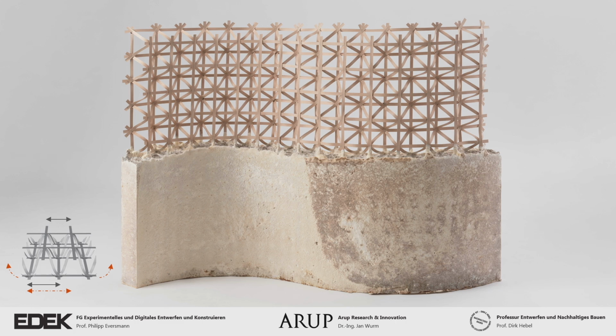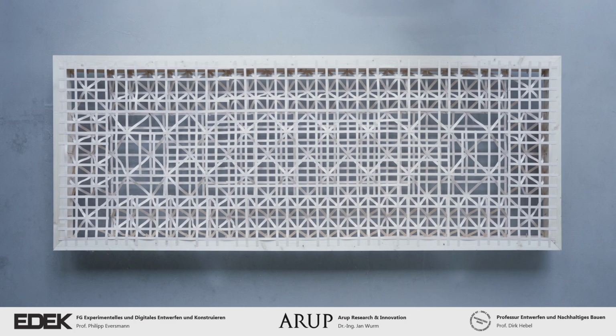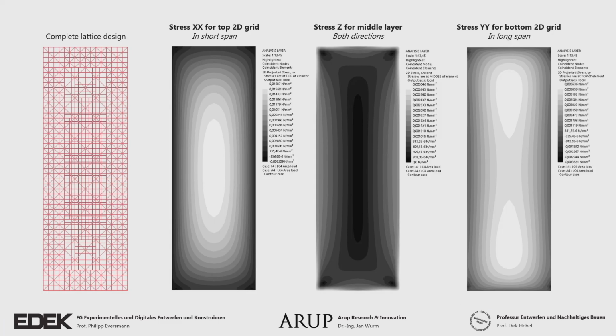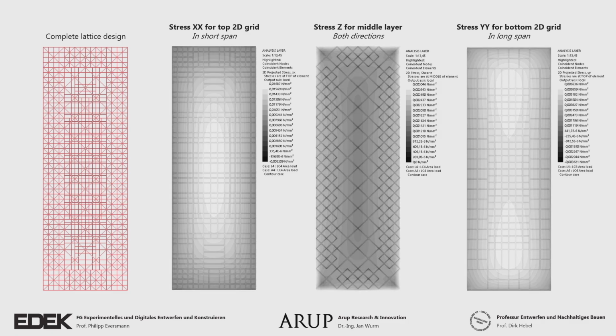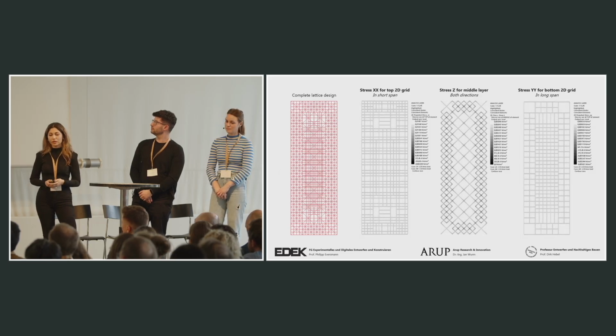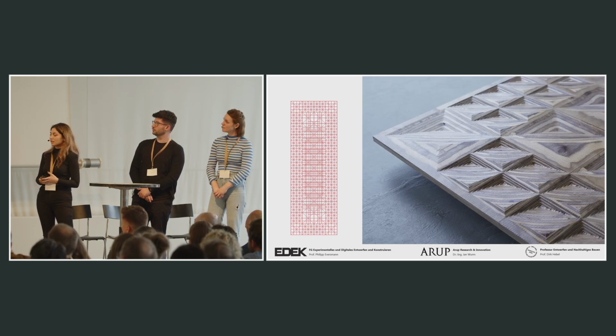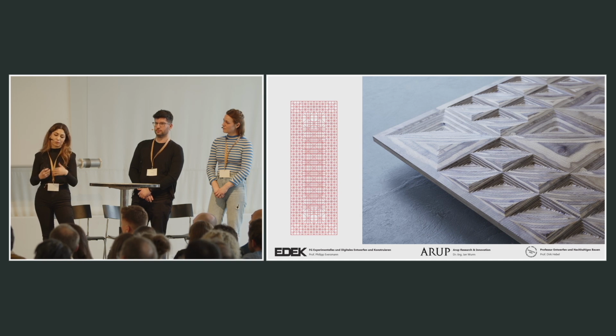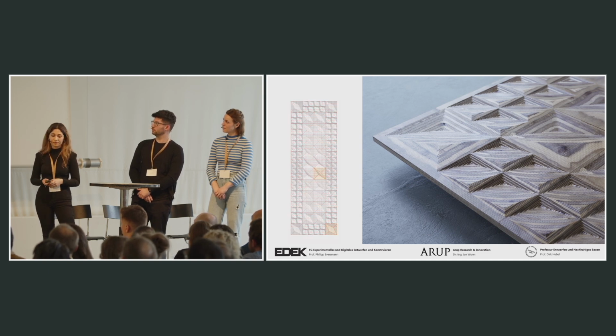Since modifying one parameter changes the geometry significantly, we went further ahead and decided to explore customizing the lattice cells, again attached to a wooden frame. Using structural analyses based on the requirements of a partition wall, we generated a lattice with 2 different cell sizes, and we used more veneer strips where we have higher stresses. We then took the cell sizes as a guide to reflect the inner reinforcement structure on the surface design. A wooden mold was used to add relief and texture to one side of the wall and to achieve acoustic benefits resulting from the surface design.